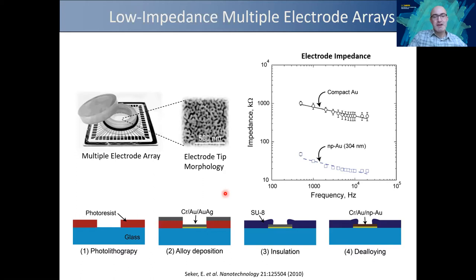So this was actually done during my postdoc in collaboration with my colleague, Dr. Eugene Berdyevsky. Typically these electrodes are made of platinum, or in some cases porous platinum, or platinum black, that is dendritic platinum. When you have a flat surface, you can only have a certain electrical impedance, because electrical impedance scales inversely with the capacitance and hence the surface area. So we thought that we could pack more surface area in these electrode sites. And this is a typical multiple electrode array used for recording from neurons for many neuroscience experiments.